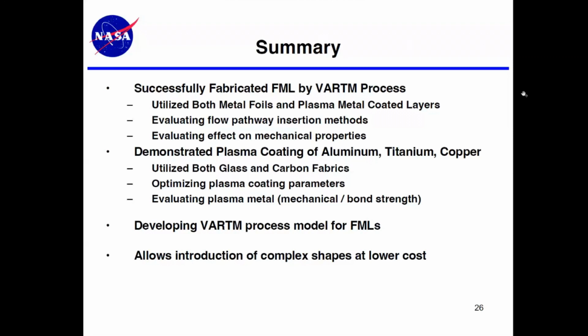There's a desire to build radiation shielding type materials for spacecraft. So we used some high Z elements as well to make radiation shielding type materials custom made. So we've also used tantalum as a deposition metal. Used glass and carbon fabrics. We have used a number of different plasma coating parameters, and they can be optimized for density, for example, of the metal coated onto the fabric.